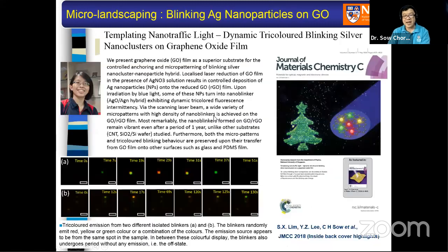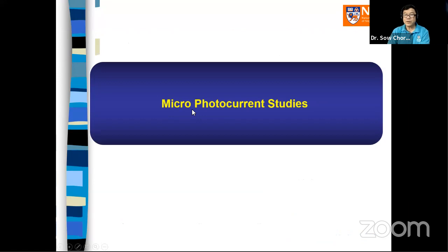And then we can also repeat the same experiment. This time around, we perform a silver reduction process on a graphene oxide film. This is work done by Sharon. What she does is her silver nanoparticle goes through a transformation from silver to silver oxide, then back to reduction to silver and silver oxide, reduction to silver and silver oxide. And this process of reduction, oxidation always resulted in particles of different size, and hence different quantum confinement effect. And these particles blink at different colors. So that's why we call it a nano traffic light. So that is landscaping.